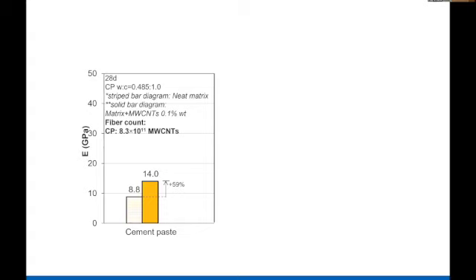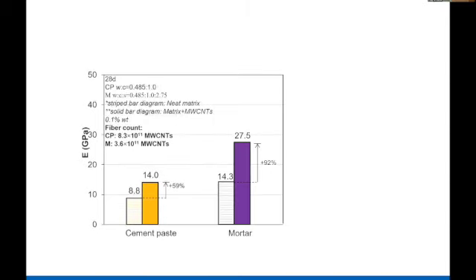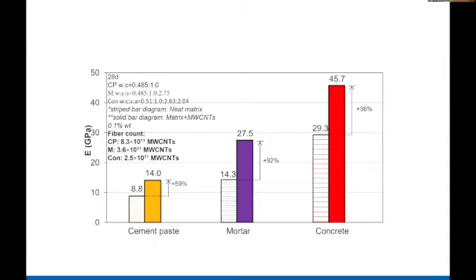But of course, high-rise buildings are not made of cement, but made out of concrete, and we are not doing anything to the aggregate. So we suspected that when we add the same amount of nanotube with sand, the effect would be proportionately less. Well, we were surprised that was not the case. This is the mortar specimen, same amount of nanotube, 0.1%. You can see we have increased the modulus even more, even though we are not doing anything to the sand. Then we checked concrete, and to our surprise, with a normal composite material approach, the increase would be very little, but here we are adding 0.1% by weight, and you can see we have increased it.